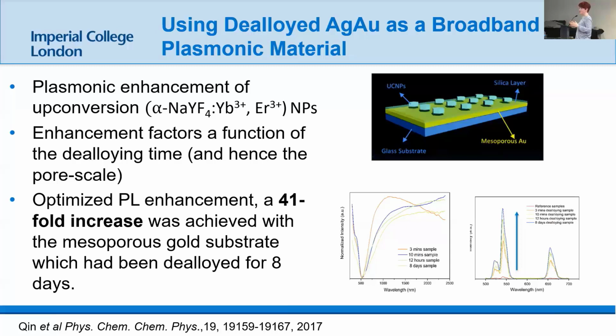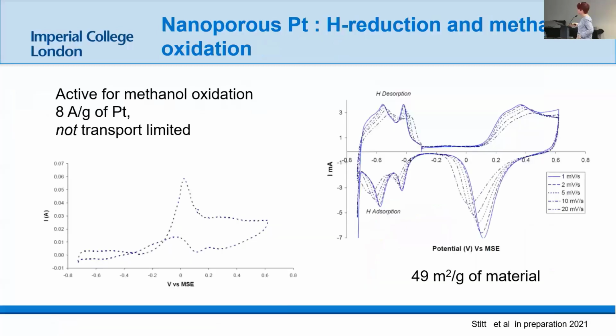And we find actually it's super dependent on the pore size of our substrate. And there's an optimum pore size, which is you dial it for 8 days, and we can speed that up, right? We know how to do it faster. But this gives us a 40 times increase in the photoluminescence intensity of this nanoparticle simply by putting them on top of a nanoporous gold substrate. Okay. The other thing you can do is think about catalysis.